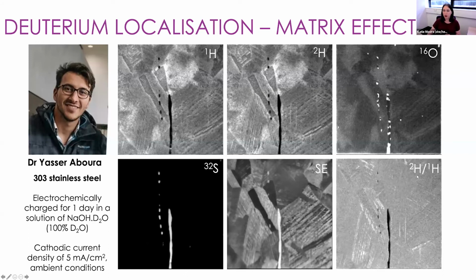We take a ratio of deuterium divided by hydrogen. And what you can see in this image is that it's basically flattened out the background in this case. We've now lost all of that grain orientation. And what's become really apparent is where deuterium is localized or enriched over hydrogen distributions. Essentially this image now shows us the locations where deuterium has been incorporated into the microstructure. So what I'm going to show you throughout this presentation will be ratio images rather than simply just the deuterium image in most cases.